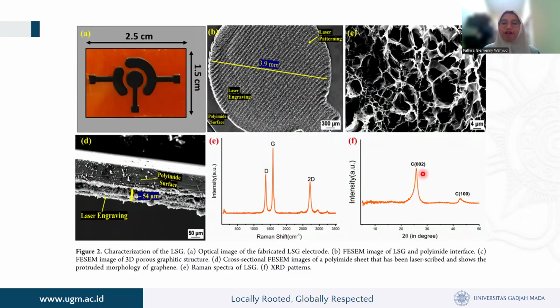This is about the characterization of LSG electrodes. Figure 2A is an optical photograph of the fabricated LSG electrode measuring 2.5 by 1.5 centimeters. The SEM image shows the laser engraving pattern on the polymer surface with an active area diameter of 3.9 mm. The three-dimensional porous graphene structure is clearly visible, showing an open morphology that increases the surface area. The cross-sectional image shows the thickness of the LSG layer at around 54 micrometers, formed on the polyimide surface after laser irradiation.